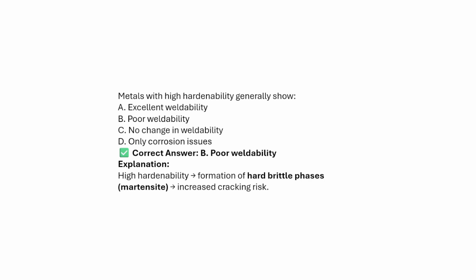Metal with the high hardenability generally shows excellent weldability, poor weldability, no change in weldability, only corrosion issues. So metal with the higher hardenability results in, as we have seen, higher hardenability means formation of hard brittle phases like martensite, and that will increase the crack tendency, the susceptibility to crack formation. So that means it will result in poor weldability.